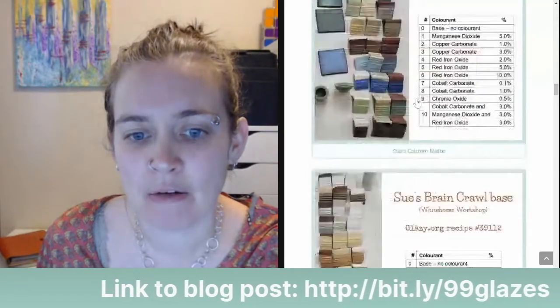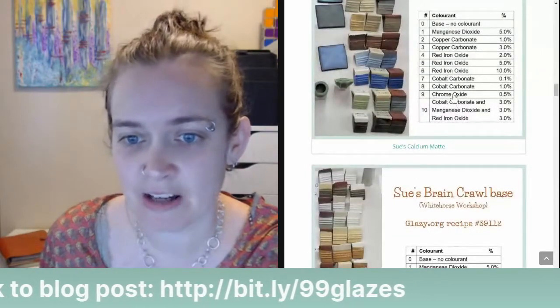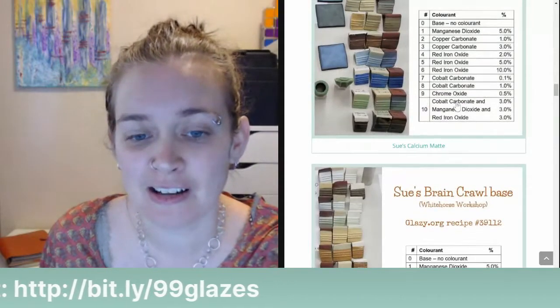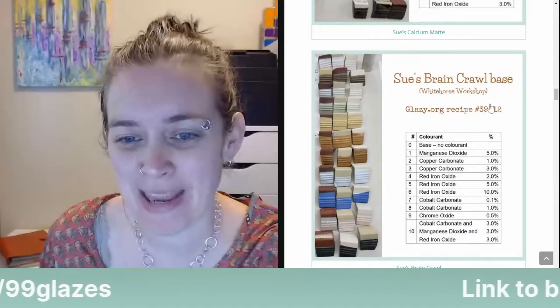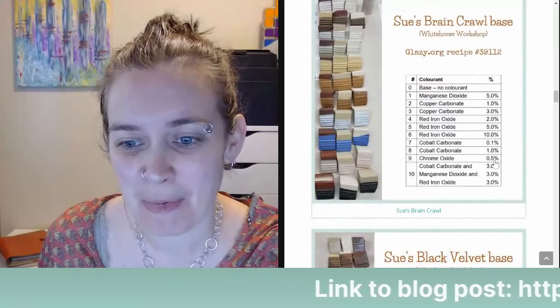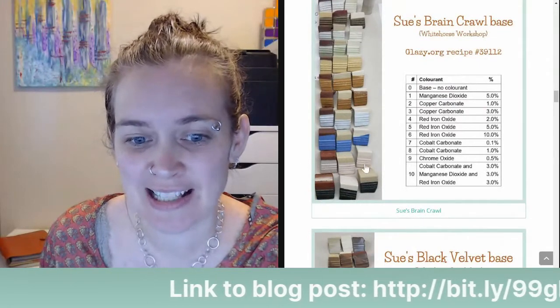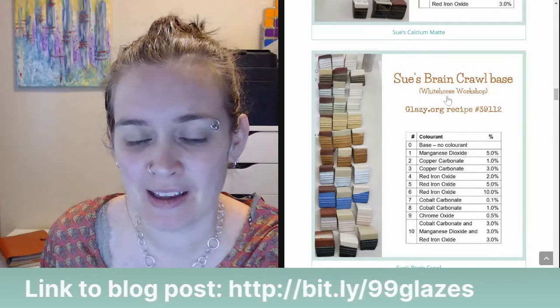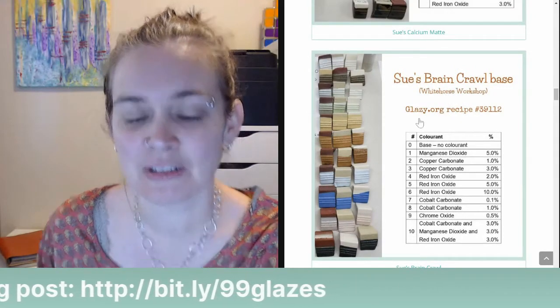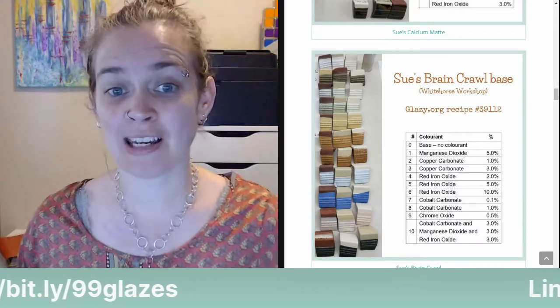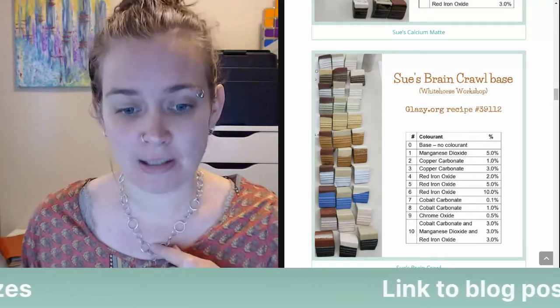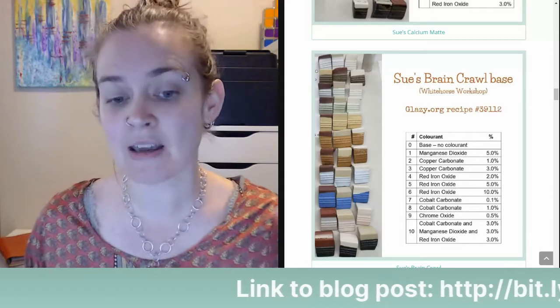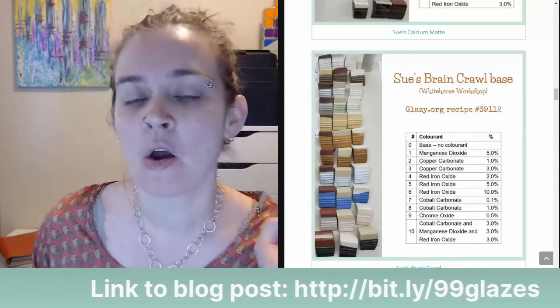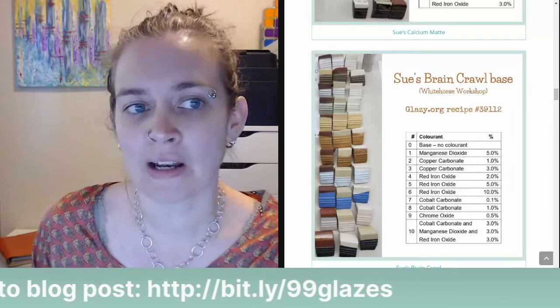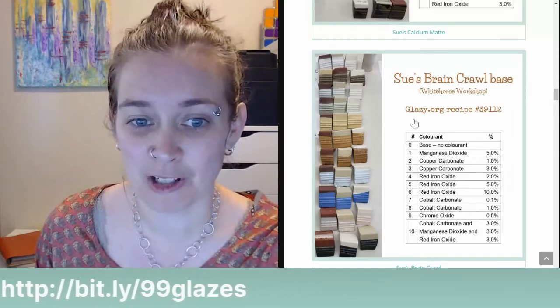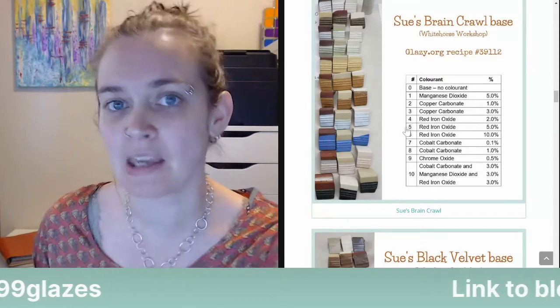Here's something interesting to see. In Sue's calcium matte, 0.5% chrome oxide turns the glaze green. And then in this brain crawl base, the same 0.5% chrome oxide turns the glaze pink. That has to do with the materials that the glazes are made of. Sometimes chrome can turn a glaze green, and sometimes it can turn pink. This recipe has a lot of magnesium and zinc, which often, when combined with chrome, will turn chrome pink. So chrome, zinc, pink, you can remember that.